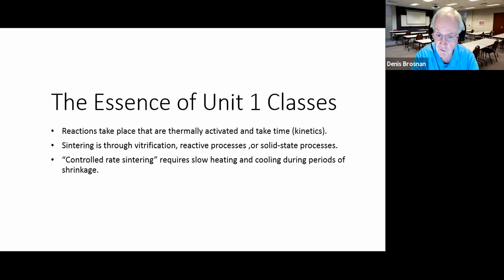Sintering takes place through vitrification in the simplest case, through reactive sintering in some cases, and solid state sintering. So the bottom line is an older term that you use, controlled rate sintering: in firing these products, you always slow down the heating and cooling schedules whenever a volume transition takes place. You give the ceramic time to go through those transformations in the firing schedule so that you don't cause cracking, either through expansions or contractions that take place too fast. That's the bottom line of Unit 1 that we've had in the course.